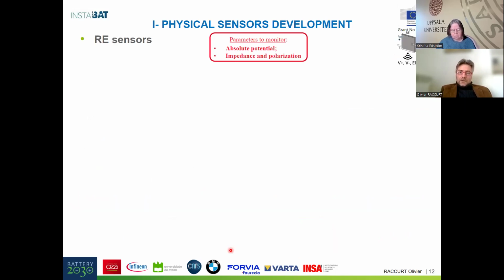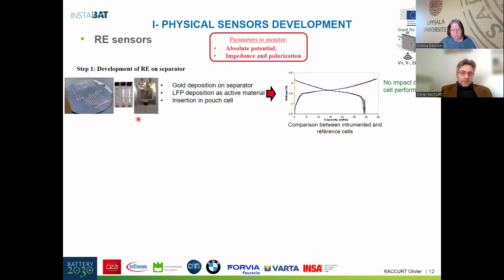Now I show you the results from the reference electrode sensor. The reference electrode sensor was developed to be integrated into the cell with a very small dimension to limit the perturbation from this sensor to the electrochemistry. For that, we decided to deposit the reference electrode onto the separators. We used gold deposition for the electric conduction, and in one part of this shape, we deposit the LFP as the active material for the reference electrode.